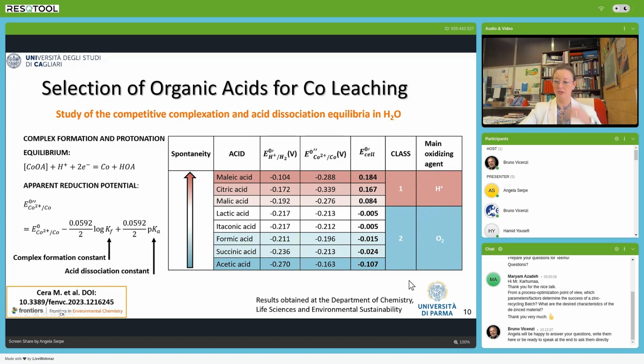So we need an external oxidant for promoting the reaction. In that sense, we can see that citric acid and maleic acid are acids that are able to oxidize the metal. Instead, for example, acetic acid or lactic acid are in class 2, so they need oxygen for supporting the reaction. Lactic acid and itaconic acid are at the edge of the two categories, so we can see that the reaction occurs also if oxygen is not present in the solution, but the efficiency is very, very low.